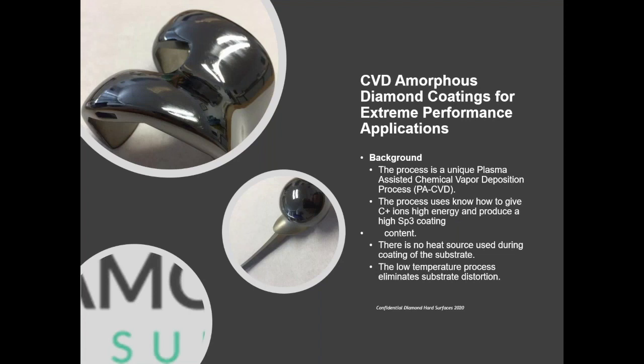Another area we're looking at, which is popping up in its level of interest again, is the ability to put amorphous carbon onto surfaces in a form that is very similar to diamond, which is an sp3 bond. A diamond is a different carbon bond from materials like graphite. There were many studies on DLC coatings 10 to 15 years ago. One of the problems with diamond-like carbon coatings is that in the past they were enabled by using methane and a hot thermal plasma process. That process introduced, without going into too much detail, a latent strain when the sample cooled down from 400 or 500 centigrade to room temperature, and that inherent strain in the material caused delamination of the thin diamond coating in some cases.